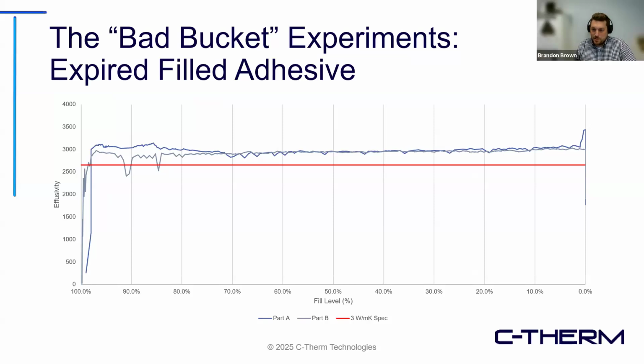Anyone can measure something good and get good results, but we wanted to make sure that we can measure bad things. So the results of the measurements here are the smoking gun we'd been hoping for. Here the buckets we've been testing were purposely expired. So testing a bad material and getting bad results in this case was a good thing. It means that we can detect good versus bad. If I recall correctly, these barrels were donated to us after not being stored in accordance with the manufacturer's directions, and it was also well past the expiry date. The results shown here are after testing parts A and B sequentially, because that's how our experiment was configured, but you could easily do it in parallel as well, simultaneously.